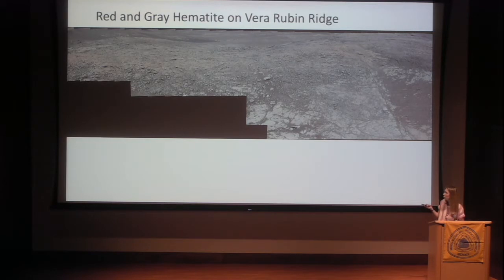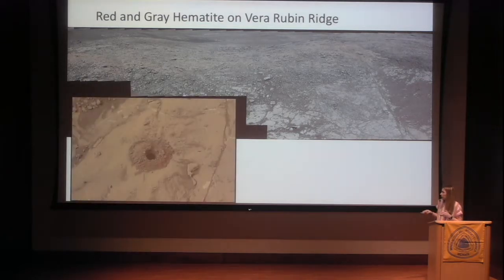This is a mosaic of the top of the Vera Rubin Ridge, and what I just want you to notice is that there are a variety of colors. Some of these rocks are red, some of them are beige, some of them are gray. And we drilled 2 of these red outcrops. This is the Stoer sample drill hole, and for scale, these drill holes are only about 1.5 centimeters in diameter. This sample had the most abundant hematite of any sample we've drilled to date, with about 16 weight percent hematite.